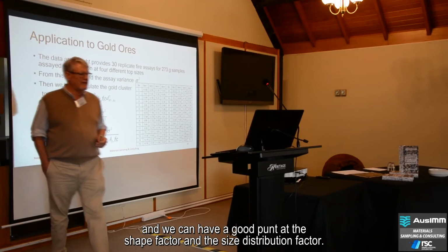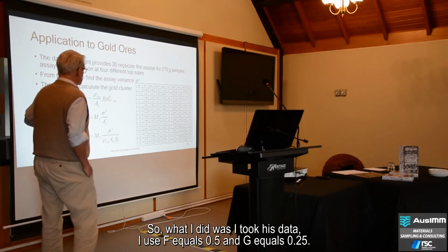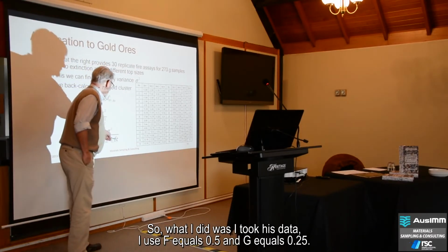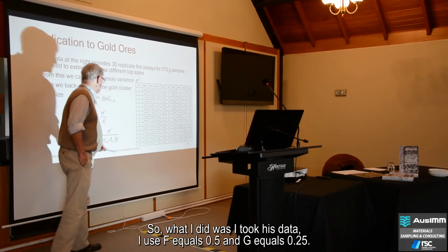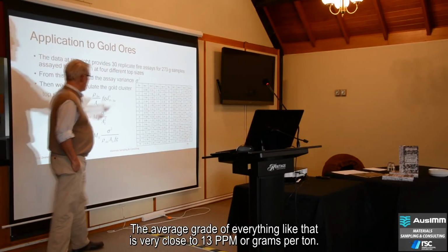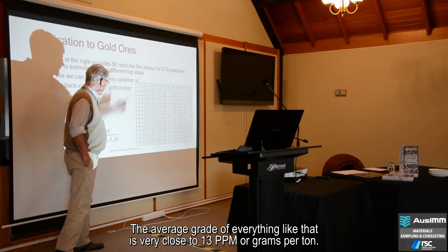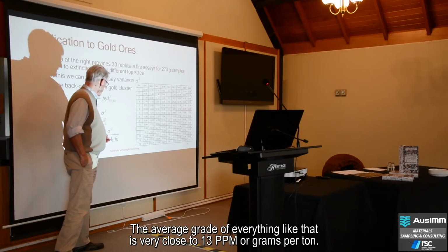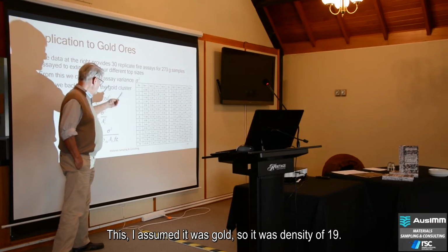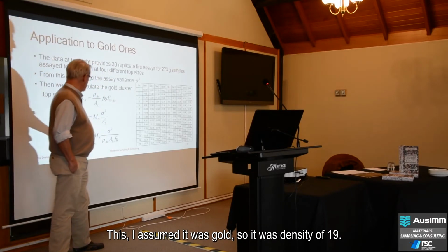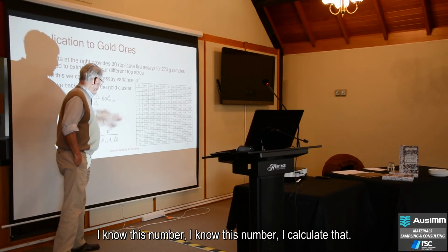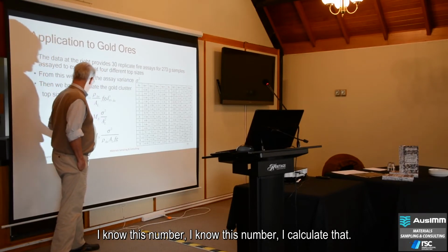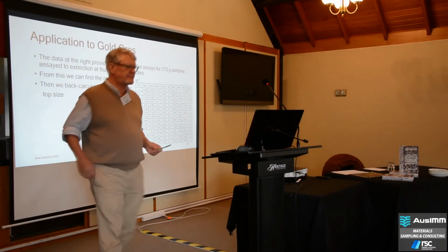size distribution factor. So what I did was I took his data, I used F equals 0.5 and G equals 0.25. The average grade of everything like that is very close to 13 ppm, or grams per ton. I assumed it was gold, so a density of 19. I know this number, I know this number, I calculate that.